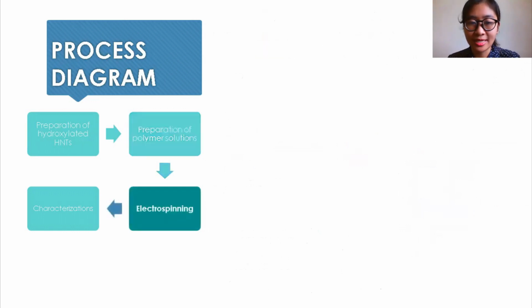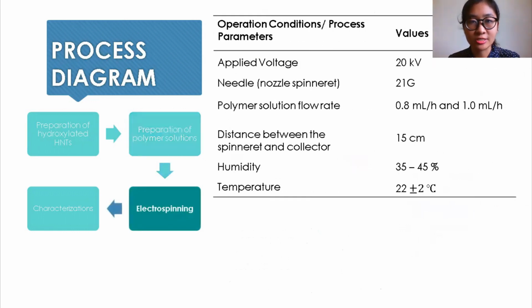As for the electrospinning process, these are the operation conditions or process parameters. The prepared homogeneous solution was transferred into a 5 ml plastic syringe with a 21 gauge blunt tip needle. The voltage was set to 20 kilovolts and a varying flow rate of 0.8 and 1 ml per hour was